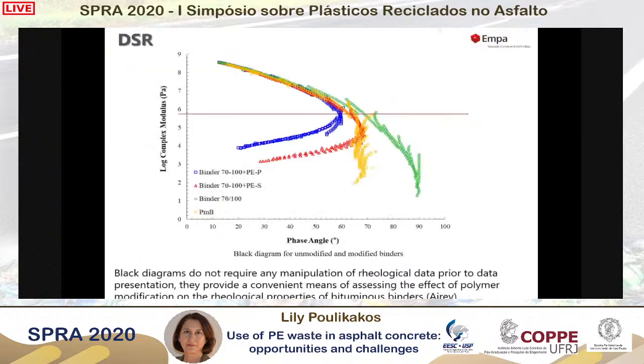as I show you the results of the mixture tests in a few minutes. Also, from the DSR results, we can look at the black curves, what we call the black curve, that shows the complex modulus versus phase angle. So this is just the raw data. There was no shifting or fitting or anything like that. So it gives us the behavior of the material.